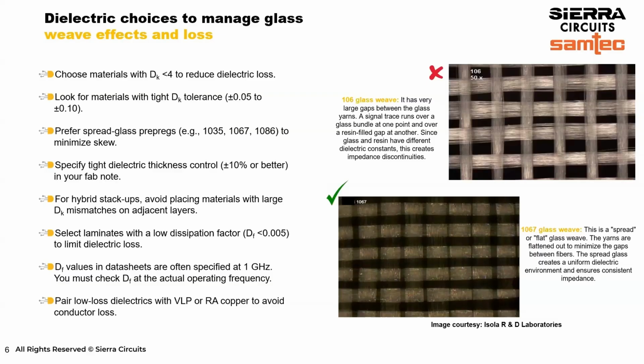Finally, don't let copper roughness ruin a good dielectric. Pair these high-end materials with very low profile or reverse annealed copper to keep your losses to a minimum.